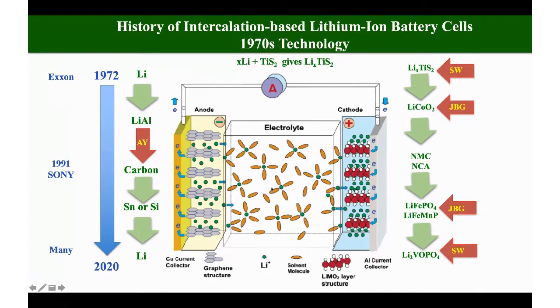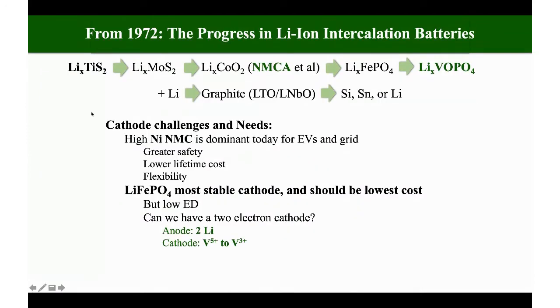On the cathode side, I already mentioned the mixed metals. John came up with lithium iron phosphate, and that was in vogue for a long time, is still probably the dominant cathode in China, and I think it's going to come back, and I'll get back to that in a moment. And we have work going on in Binghamton on the manganese analog of that. This is 4 volts versus the 3.5 volts of iron. And on the research stage, we're basically saying we've got to get more lithium in per transition metal if we're going to use these safe phosphates. So we're looking at these vanadium phosphates. So let's just look at this in more of a linear form.